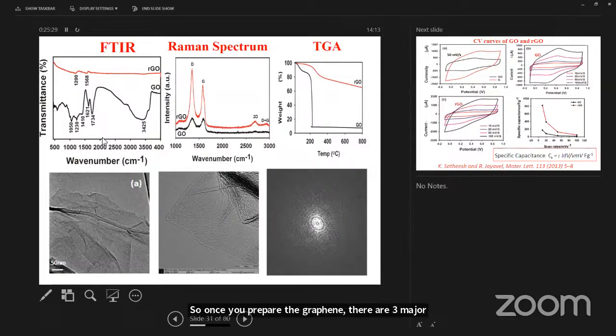to check the extent of reduction. Here we have different kinds of oxygen functional groups like carboxyl, hydroxyl, carbonyl, and epoxy groups. If you are able to reduce all the oxygen functional groups, then it becomes graphene. But many a time, we have some residual oxygen functional groups. Therefore, we call it RGO. And this is the Raman spectrum, which shows the D and G band peaks. And sometimes, if we have a stacking of a few layers, then we also get the overtones, the 2D and D plus G peaks, at the higher wavenumber.